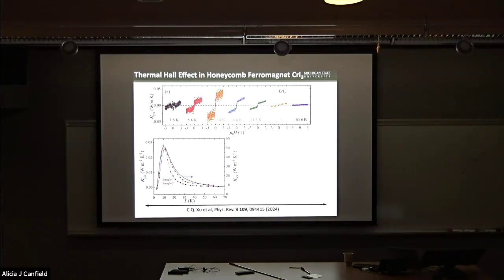There are two features I would like to point out. First is at low temperature. Again, the thermal Hall signal maximizes. Right? It peaks somewhere about 10 Kelvin. And for both samples, it turns out that this peak position is almost the same as the peak position that we can see from the longitudinal thermal conductivity. So again, this tells us that similar to the vanadium triiodide, for the chromium triiodide at low temperature, the thermal Hall signal can be dominated by the